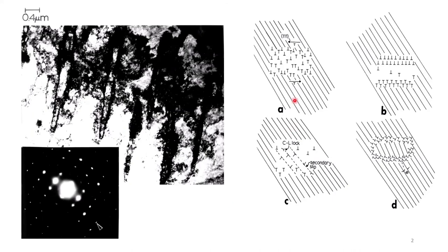Talking about how they're formed: you have some shear going on as a result of the hypervelocity impact, and you start forming dislocations. We learned early on in our metallurgy curriculum that when you start bending or forming metal, you form dislocations. The hypervelocity shockwave creates an order to these dislocations. We end up with Lomer-Cottrell locks and secondary slip starts to form on secondary slip planes — and this secondary slip is what leads to the formation of microbands characterized by the 15-degree misorientation angle.